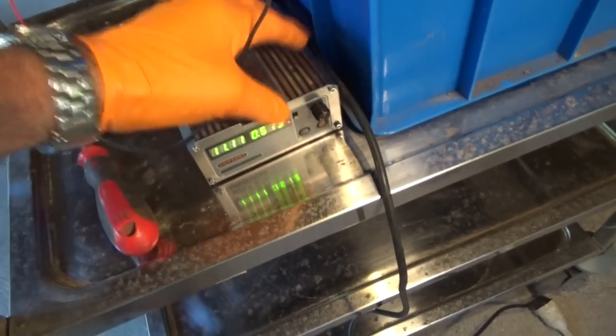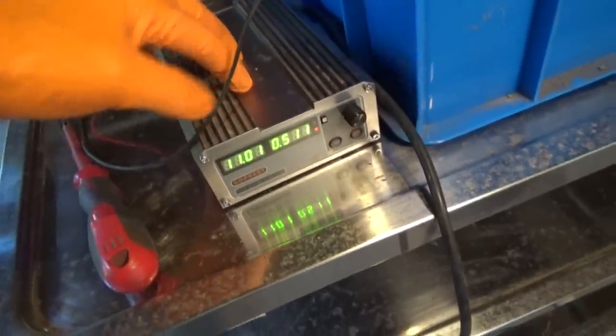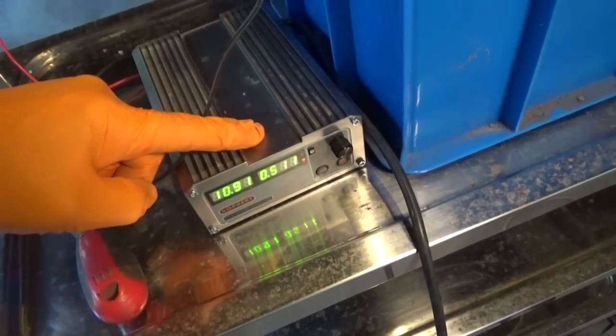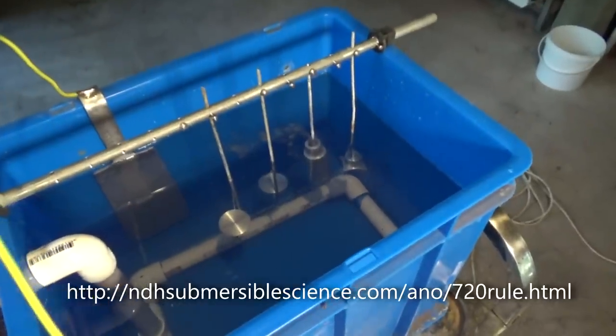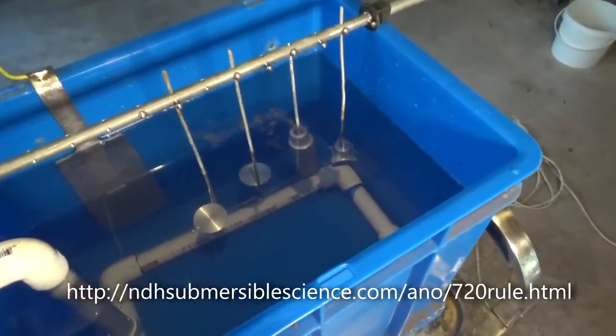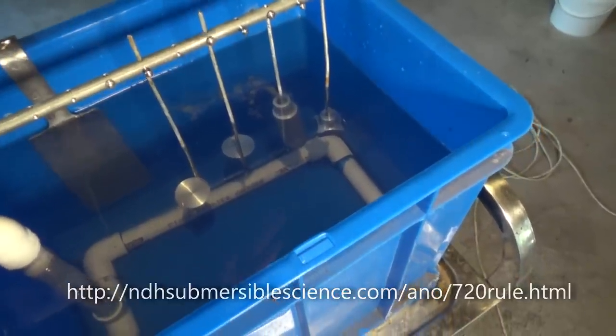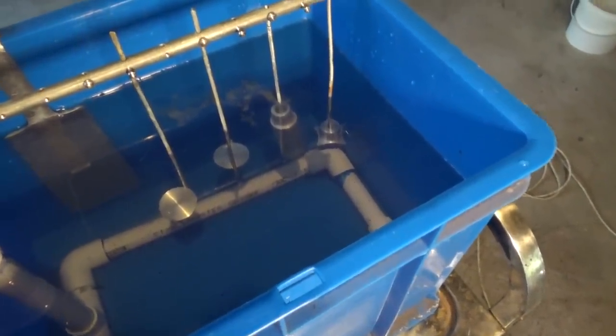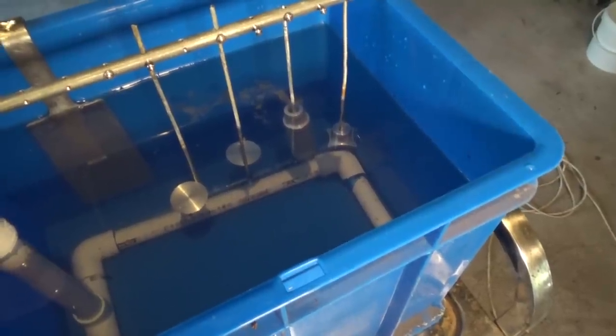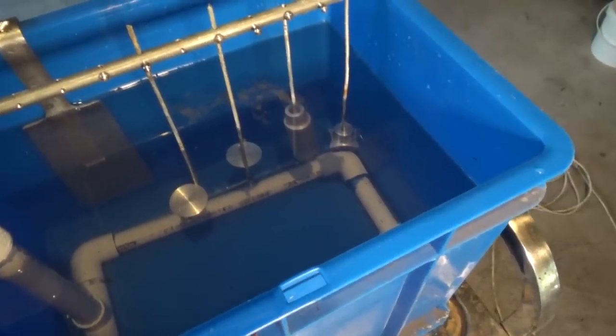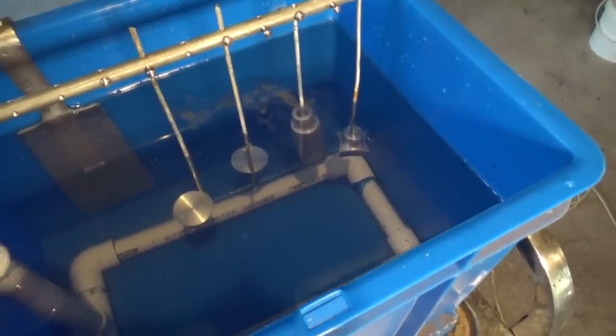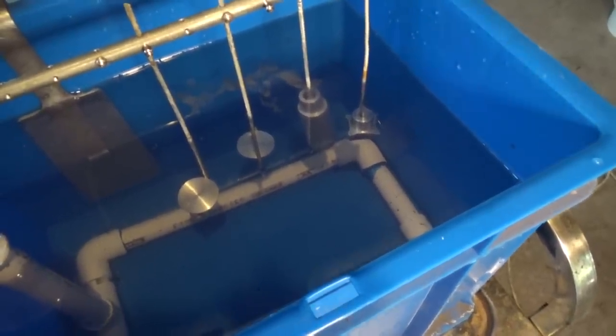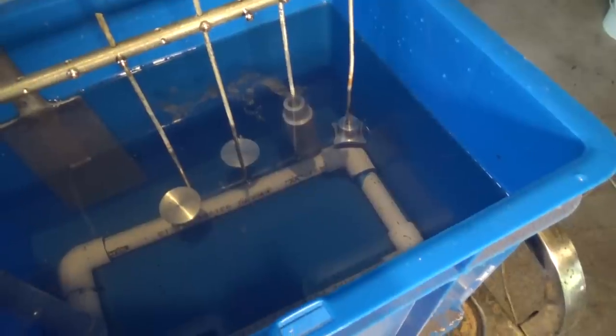Now I've got this set to 15 volts. If I turn the volts switch over you'll see that it's showing 15 volts. But in reality it drops down lower than that, sitting on about 11 at the moment. I've got my amperage set to about half an amp. There are various calculators that allow you to work out supposedly exactly the voltage and amperage that you need. However in practice I've found that it doesn't really work. The problem is that you need to be able to work out the surface area of all your parts. Some parts are so convoluted and complex that would be a difficult task. Even when I've done that I find that the actual amperage being drawn by the parts is nowhere near what the calculator said it should be.